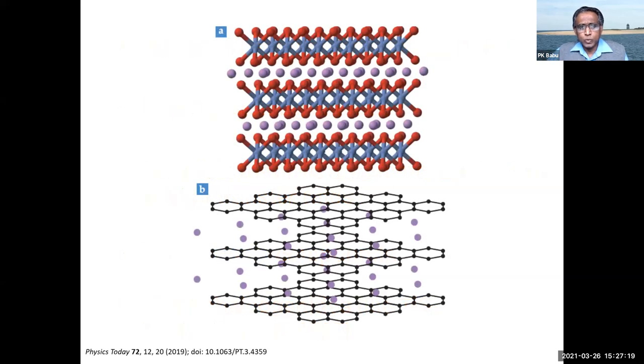This cartoon depicts the intercalation mechanism, which I told you. This is a layered compound with a lot of space in between. Lithium atoms can actually go and stay in that. Say, for example, during the discharge phase of your storage battery, and when you apply a voltage or pass current through that, you can push these lithium ions back to the anode part of the material.